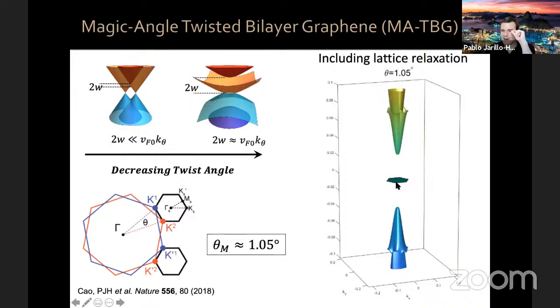When you have that very, very small bandwidth, interaction effects become very pronounced. They acquire a very big importance because your kinetic energy is quenched. Your electrons don't have kinetic energy now, very little. That's why all of this physics occurs near 1.1 degrees, because your kinetic energy gets very much reduced compared to interactions, okay? And that's why all of these strong interaction effects become pronounced.